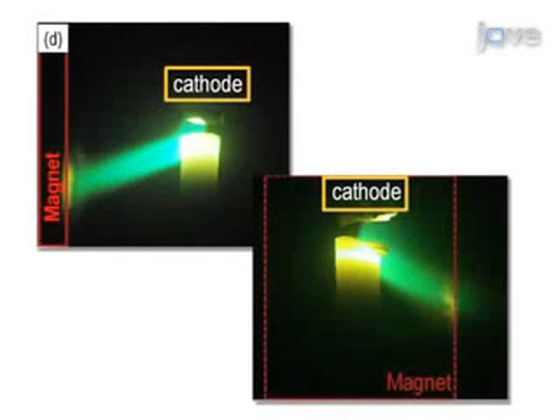Shown here are video snapshots obtained simultaneously from the right and front viewports of the chamber for an electrode gap height of 75 millimeters. These images illustrate significant perturbation of the arc plasma column in the presence of an external magnetic field.